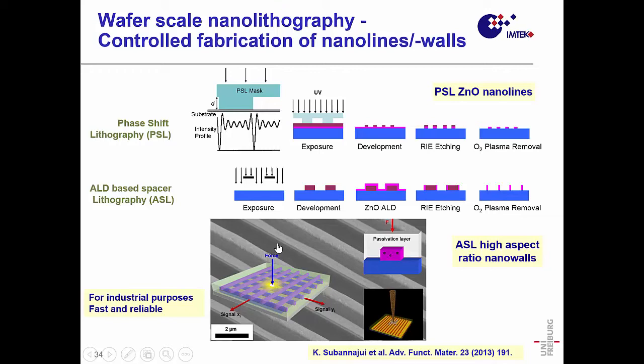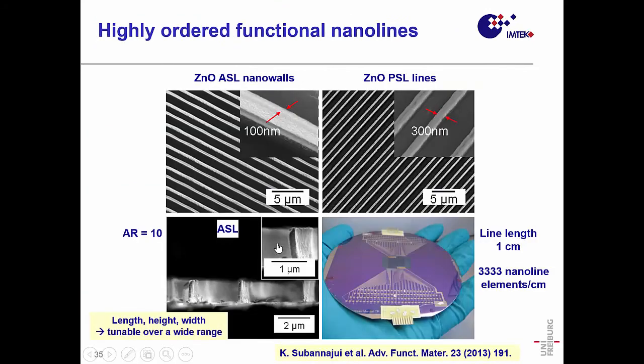One is we first prepared a layer of zinc oxide by our ALD system, and the second one is we prepared a resist line pattern, and then we overgrew that by ALD. ALD has an advantage, you can do that at low temperature, and that means you can even overgrow a resist line, and then you do an etching of the top a little bit, and then remove the resist and have these nanolines. Let's show the mechanical properties and how that looks like.